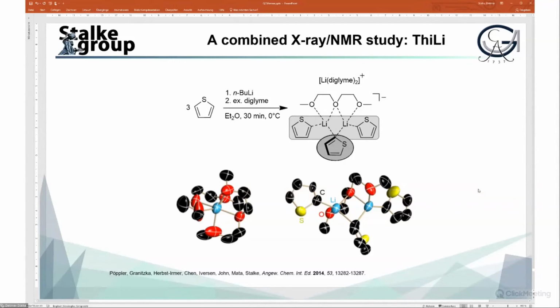We couldn't really figure out what is this in the solution with diglyme. With a diglyme donor, you create a lithiate. So what we do is we surround one of the lithiums with 2 diglyme molecules, which is the cation. And the anion is made from 3 anions only coordinated to 2 cations. And then one of the diglyme is bridging the 2 lithiums. And that, of course, wasn't on the card at all, so we didn't envisage that molecule to be around.